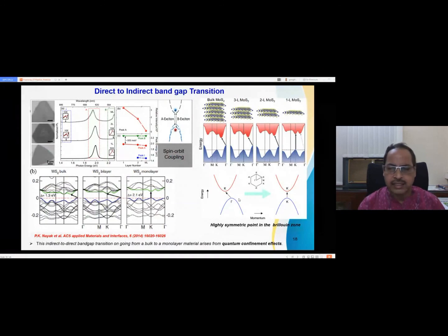Another interesting property of this material is the direct to indirect band gap transition. So what is this? This is a direct band gap. You can see the E versus K diagram. This is K to K momentum direct band gap. This is indirect band gap. But mostly for our optoelectronics application, we want a momentum direct band gap, because you have electron hole recombination, and you have to extract the electron hole or exciton dissociation. So that's why for optoelectronics application, direct band gap has much more advantages over the indirect band gap.